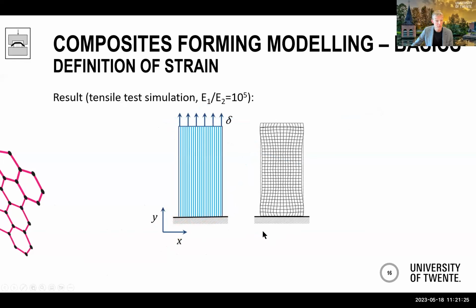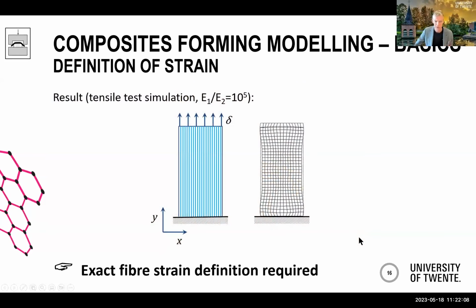The effect of that is if you would do a simple tensile test simulation, fibers in one direction with a modulus ratio of 10 to the power 5 over here, then this is what comes out in a classically okay nonlinear calculation. And this is then the converged answer. Okay, so we thought this didn't make a lot of sense, and that's why we went into ways to accommodate these things and to figure out what was actually happening. So, I'm not in the position to give any commandments, but I would definitely advise to use an exact strain definition when describing large deformations during composites forming with this kind of anisotropy ratios.